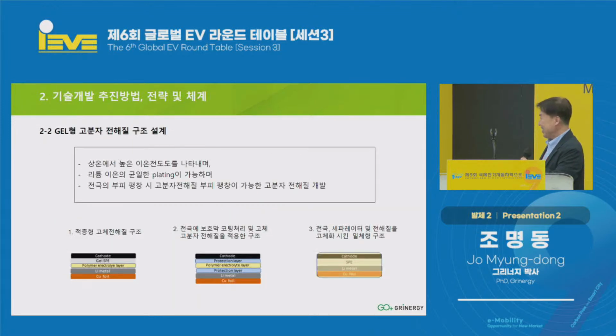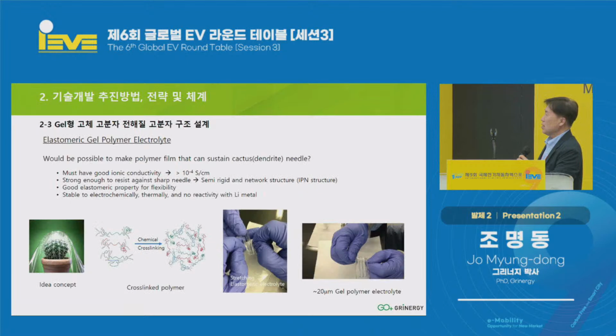Sorry, my slides are going backward. So the 3 layers were the system that we have applied. It's simple, but still the best approach. On top of that, there is a protective coating, and it also has a special property for flexibility, and it's very stable. And in the design of the solid polyelectrolyte polymer, when dendrite keeps accumulating, once again, the separator that divides this will also increase. And although they keep suppressing the growth of the dendrite, we can stop the anode and cathode from being separated. However, there are also issues.